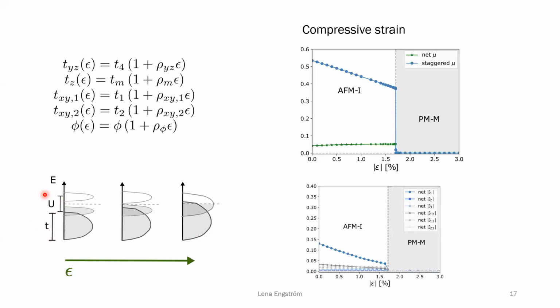It doesn't affect the interaction at all. So the effect is that the bands become broader, but the energy scale of the interactions remains the same. This means that as we increase the strain, we get broader bands and a smaller gap. It's harder for the interactions to sustain the order that we have. And eventually at some strain, we will get a phase transition where we no longer have an antiferromagnetic state.